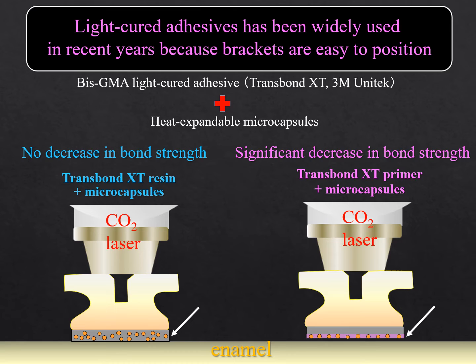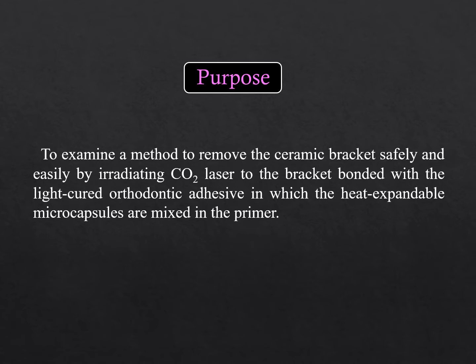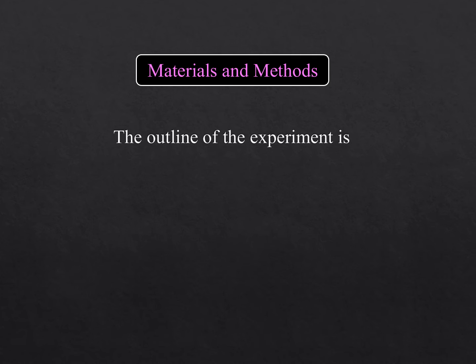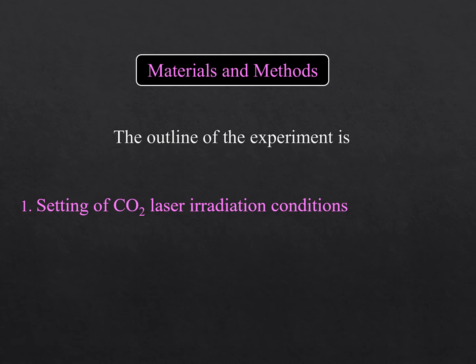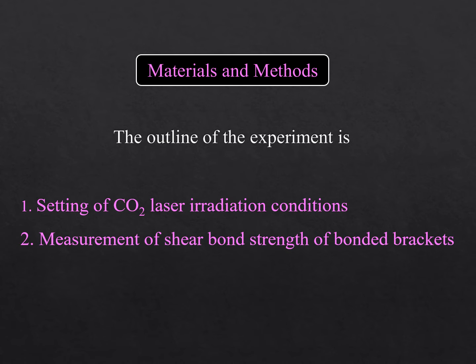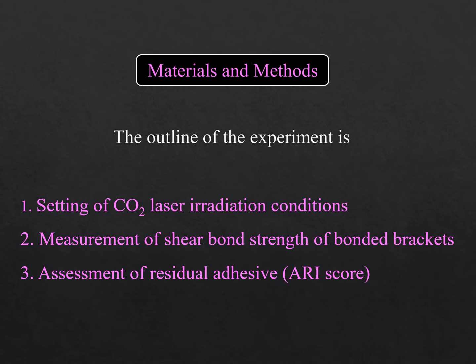Then, a detailed study was conducted under these conditions. The purpose of this study was to examine a method to remove the ceramic bracket safely and easily by irradiating CO2 laser to the bracket bonded with the light-cured orthodontic adhesive in which the heat-expandable microcapsules are mixed in the primer. The outline of the experiment is setting of CO2 laser irradiation conditions, measurement of shear bond strength of bonded brackets, and assessment of residual adhesive.